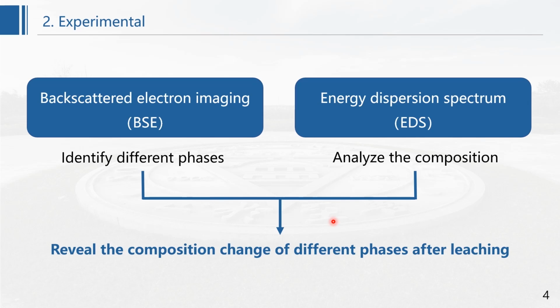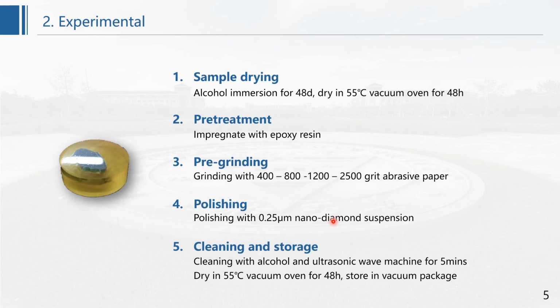phases in PC. In this investigation, we mainly use BSE to do the characterization, so we need to prepare samples for BSE test. We polish the sample following this process.